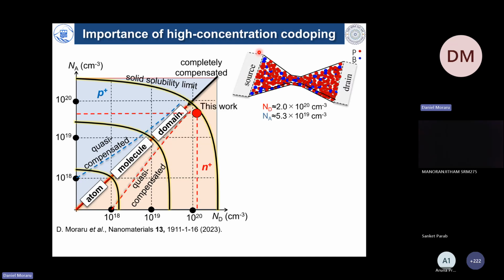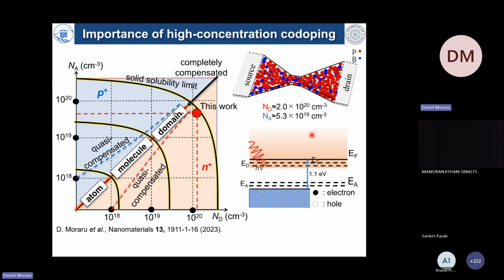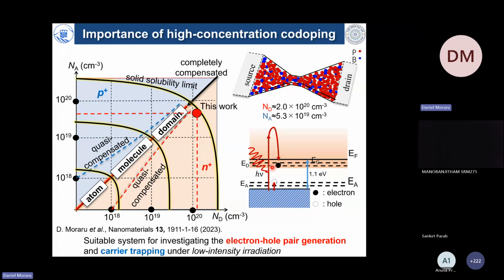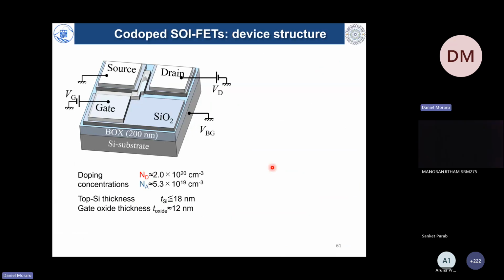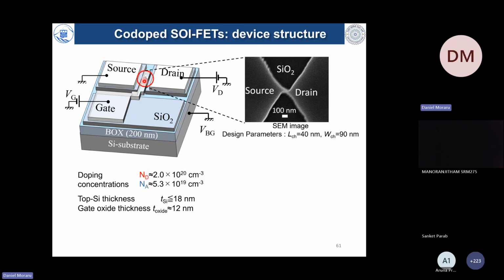So we built this kind of transistors with doping concentrations illustrated here, and then we hoped that by irradiating light here, electrons and holes can be captured both in donor states and in acceptor states simultaneously. This could enhance the sensitivity for carrier trapping in our devices. So together with researchers from IIT Roorkee visiting my lab for several months, we studied co-doped SOI-FETs like this, with these parameters shown here, but with the top gate removed. What we have between source and drain is an extremely tiny channel, which is just a few tens of nanometers in width and length, and it looks like that.